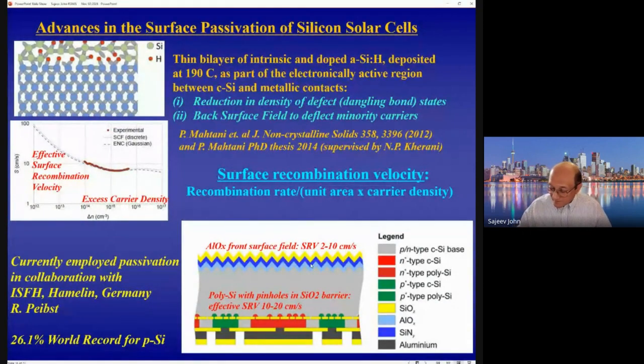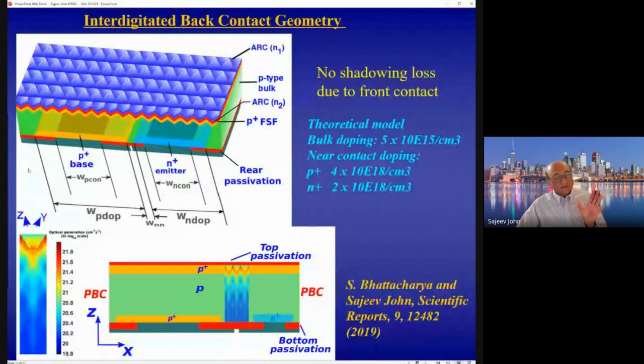And they use something that's called interdigitated back contact configuration, which moves both the positive and negative contacts to the bottom of the cell, shown in the two sets of black regions at the bottom of the cell, so that there's no shadowing loss or reflection of light at the surface due to the presence of contact. So this is another way of allowing more sunlight to be absorbed. So this is the design of the structure that we're actually considering. It's slightly different from the one by the German group, but quite similar.